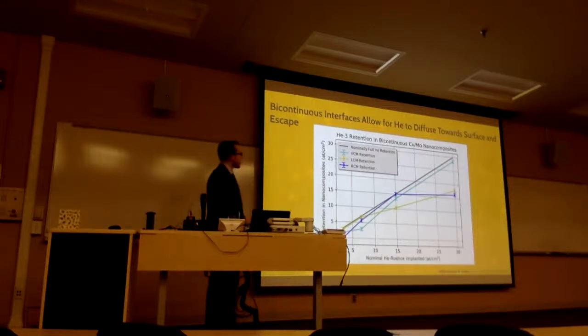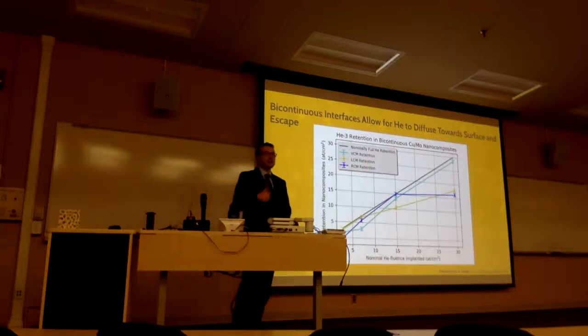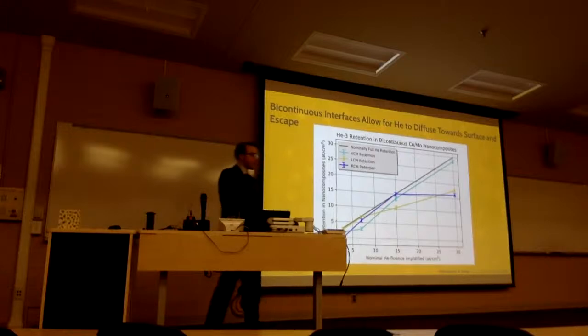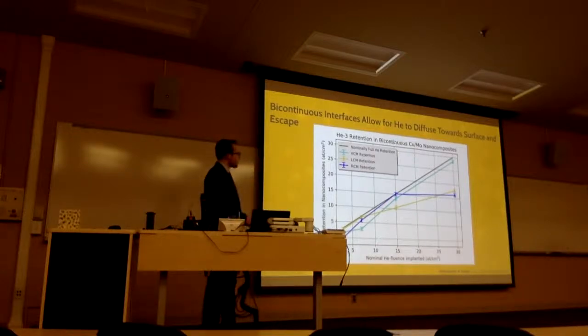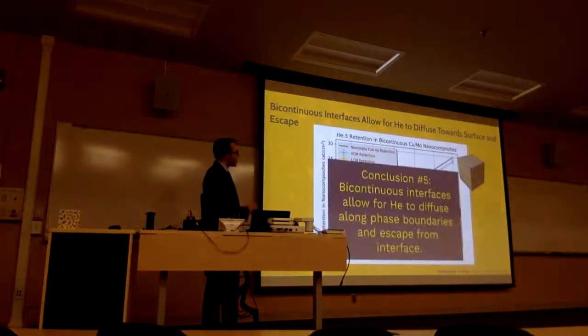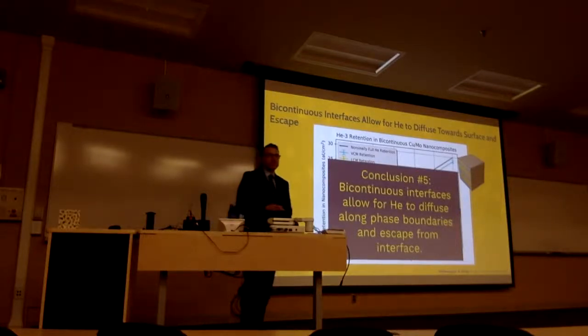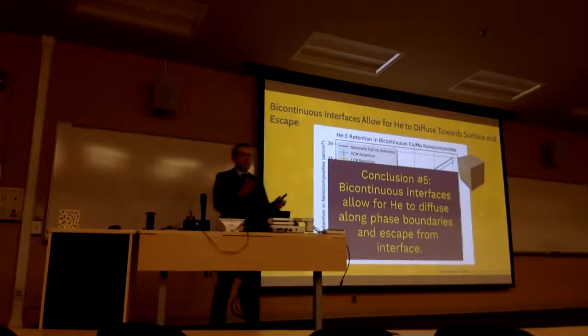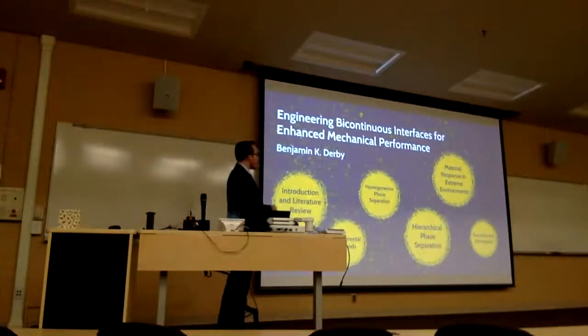What I hope you can see here is that the LCM and RCM morphologies actually allow for some of the helium to escape at high fluences. You can see as we increase the fluence, that retention of helium inside the sample starts to decrease. So what we think is happening, and these are the representative morphologies, is that bicontinuous interfaces actually allow for helium to diffuse along the phase boundaries and escape from the interface at the surface.